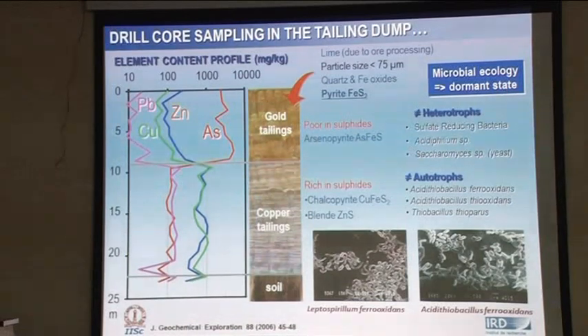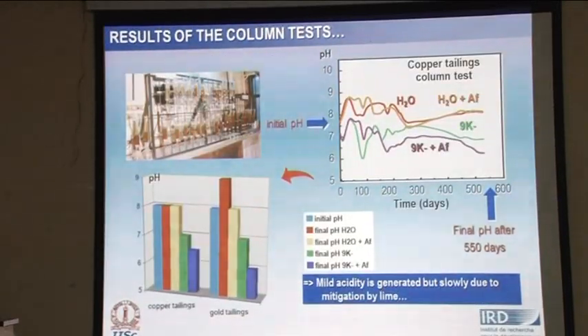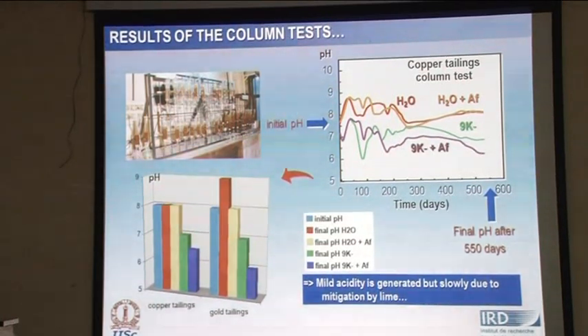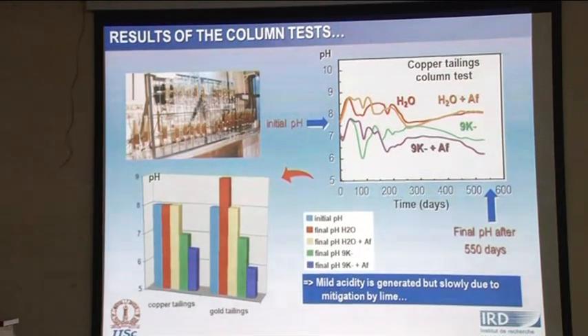So when we did the tests in columns, these are long-term tests conducted in columns. We erected columns there. We took the tailings and we carried out these studies over an extended period of time, over 550 days. And as you can see, under different conditions, you have the acidity getting generated. So we did some control tests in the absence of bacteria and in presence of bacteria. So fortunately for us, because of the pyrite, to depress the pyrite, lime is added in the flotation process, as you all know. So the lime that is present there in a way acts as a buffer, and the acidity generated is not much.